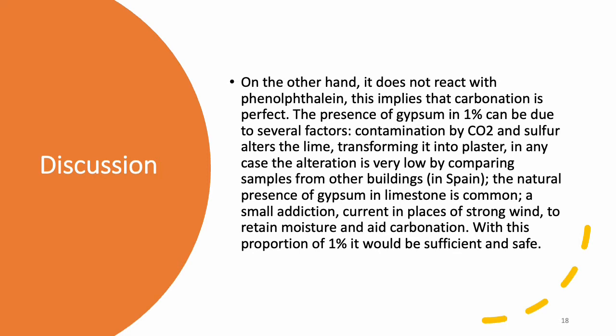The presence of gypsum can be due to several factors: contamination by CO2 and sulfur alters of the lime, transforming it into plaster. In any case, the alteration is very low by comparing samples from other buildings. The natural presence of gypsum in limestone is common. A small addition, current in places of strong wind, to retain moisture and aid carbonation. With this proportion of 1%, it would be sufficient and safe.